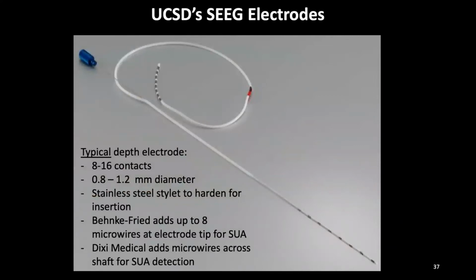But first, how does a clinical depth electrode look like? This is what this picture is showing us. This is an AdTech electrode, typically has 8 to 16 contacts at the surface. They are a few millimeters spaced from each other. Each contact can be 2 to 3 millimeters in terms of its extent, sometimes larger. The diameter of the electrode is at smallest 0.8 millimeter, at its largest it could be larger than 1.2 millimeter, but for epilepsy monitoring, usually the range is 0.8 to 1.2 millimeters.